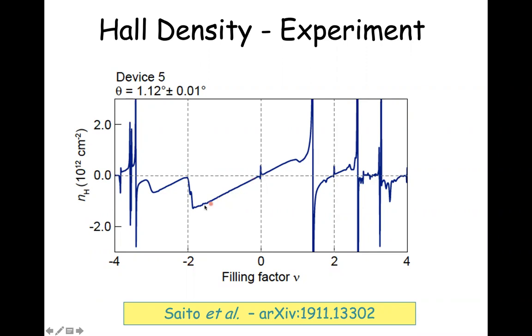And this is the region of filling factor, Moiré band filling factor, that I was pointing to before. Here, filling factor is measured from 0 to -4 for the valence band, because there are actually 4 bands, and 0 to +4 for the conduction band. And what you can see here is that the density is changing linearly, just as it should. And this is perfectly consistent with the Shubnikov–de Haas measurements. But then something happens near -2, and that something happens at an even lower density on the electron side. So what is that something?